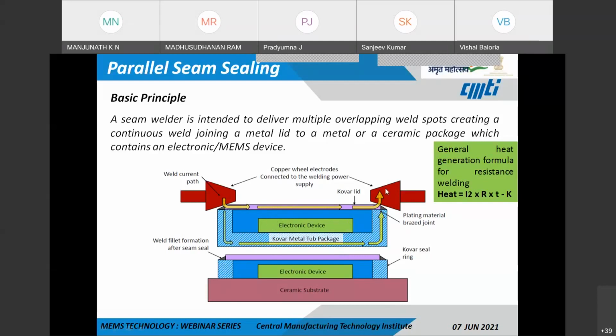So it is basically a type of resistance welding where the power is passed through the tapered electrodes, where you see the weld current is passed through these tapered electrodes. And then since the resistance of this interface is higher than that of either the lid or the case, the heat gets concentrated at the seal and reaches almost about 1500 degrees. So at the interface of this seal, the temperature will rise to about 1500 degrees.